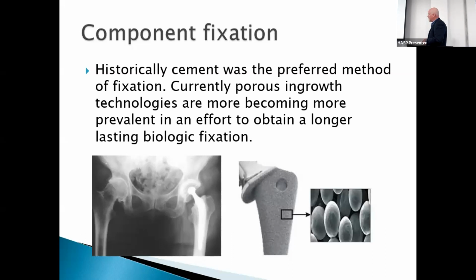And there's been a long history of development of what's the best type of implant for cementless fixation. What's the best metal? Do we use beads that are sintered onto the surface, or the other option for most is a titanium plasma spray that sprays the titanium in a pattern that mimics that porosity of bone. The majority of the evolution of cementless implants over time has gone from stainless steel with sintered beads to titanium components with this plasma spray, because the body really accepts titanium very nicely as a very bone friendly option, because bone tends to ingrow into titanium better than it does into stainless steel.